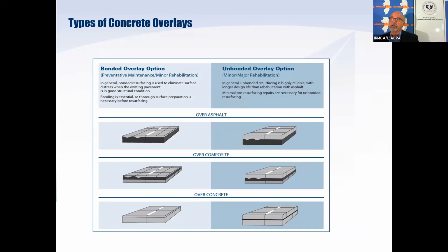When you're dealing with the bonded overlay family on the left-hand side, the bond becomes an integral part of the design. The concrete and the asphalt bond together to form a monolithic structure. So we actually have some of the load carrying capacity of that pavement embedded in the existing asphalt. On the right-hand side, you'll see a concrete overlay over an existing asphalt pavement, but it seems to be much thicker. That is because it is.